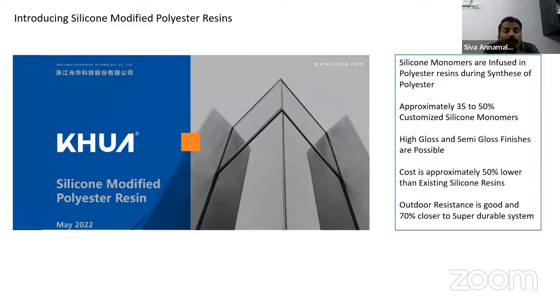And most important, this can be used for outdoor applications. With normal silicone resin, nobody looks at the weathering property because the shade itself is a dead matte kind of texture product. Whereas this one can give us outdoor performance very close to super durable. I am not saying it is as good as super durable, but it is better than standard PP and very close to super durable. So you can get 70% of super durable performance with this polyester. Very few people have developed this. This product is called SMP, silicone modified polyester resin.